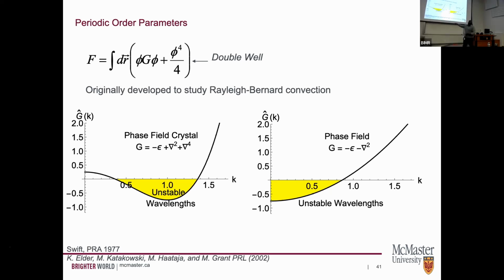If I change this particular kernel and I happen to add an additional surface contribution, it turns out that I move that stability to somewhere where I could stabilize different structures. So I didn't develop this. This goes back to Swift and Hohenberg back in the 70s. And they used it to look at convection instabilities. And so what you have is a liquid, you heat underneath it, and then you form patterns that look like this.